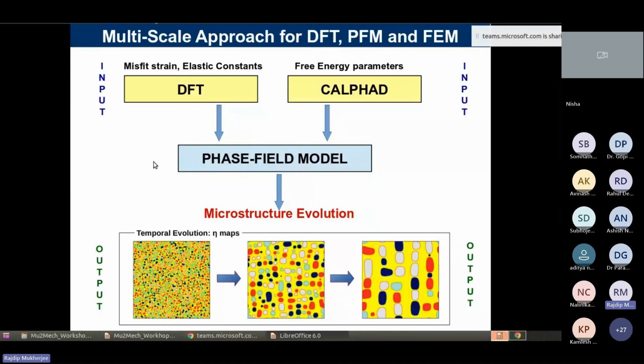So density functional theory, why do we use it? Because we need several inputs for this phase field model, like misfit strain, elastic constant, interfacial energies. All these calculations can be done using density functional theory calculations or molecular dynamics simulations, mostly atomistic simulations, right? So their output will act as an input for a phase field model, which you can use to study the microstructure evolution, right? The second thing is the free energy, right?